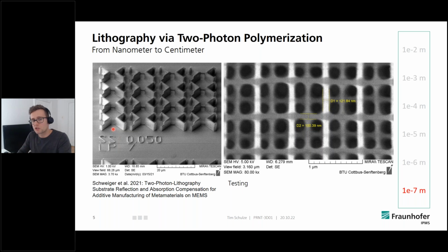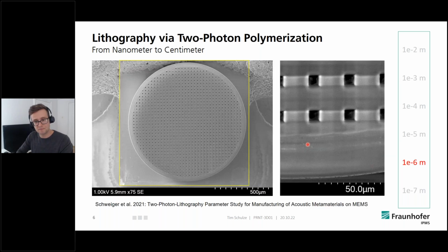Yeah, because sometimes we had issues when printing really special structures that the intensity was too high on top of the substrate, and then bubbles appear, and with these parameter sweeps we find the proper printing parameters. And this was just a test structure we've done. It is those prominent wood piles, so just single lines printed in this wood pile configuration, and you can see here that we were able to reach a width of approximately 100 nanometers. So let's scale up the size of it.